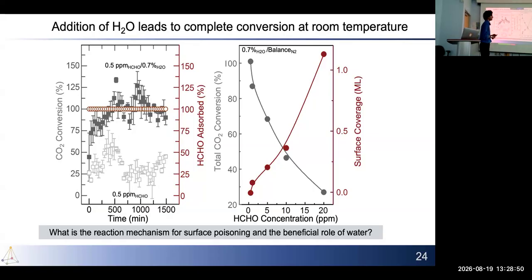So now the question is, what is water doing in accelerating the CO2 conversion? And then again, this is only valid at low concentrations. Once you increase the concentration, the conversion again dies. So there's something really strange and interesting that's happening at about 0.5 ppm of formaldehyde.